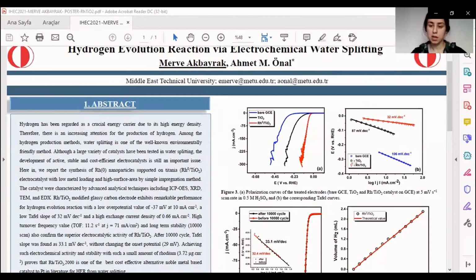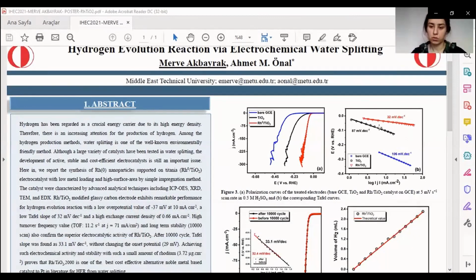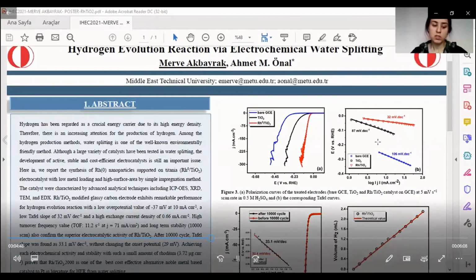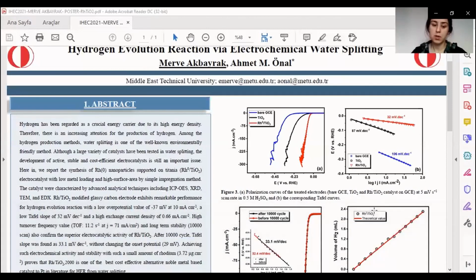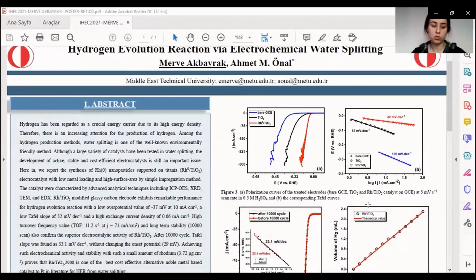Tafel slopes of the bare glassy carbon electrode, titania and rhodium titania modified glassy carbon electrode were calculated as 106, 87 and 32 millivolt per decade respectively in figure 3B. The overpotential values at 10 milliampere per centimeter square current density for rhodium titania and titania were found to be 37 millivolt and 104 millivolt versus reversible hydrogen electrode. The lower onset potential of rhodium titania makes it superior over most of the reported rhodium-based catalysts.